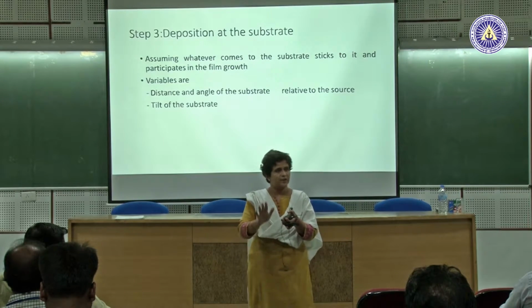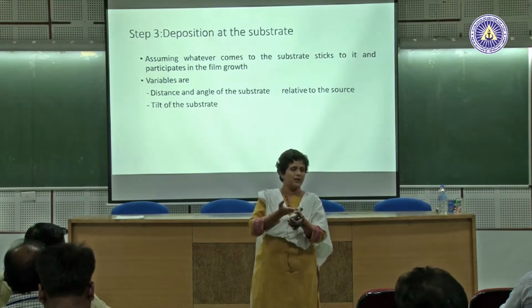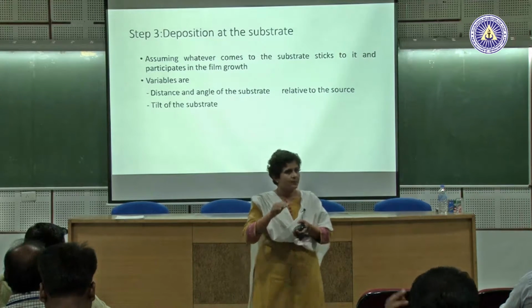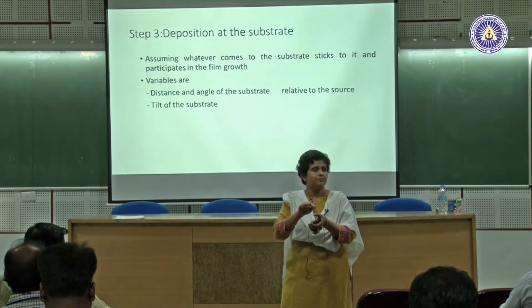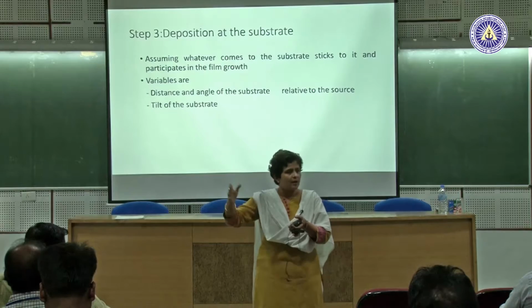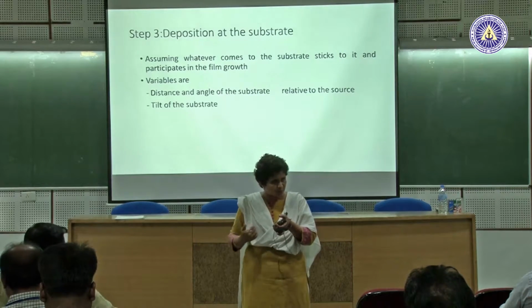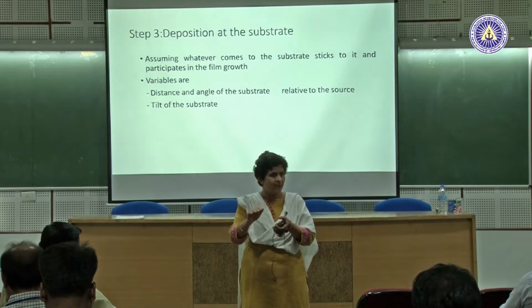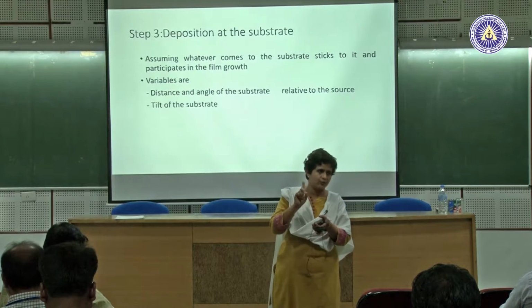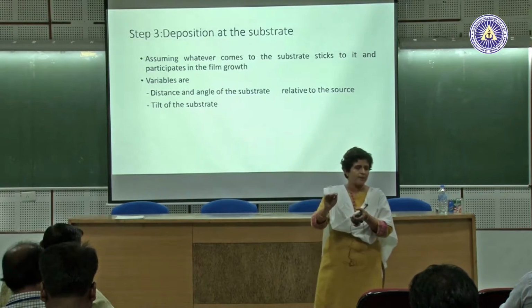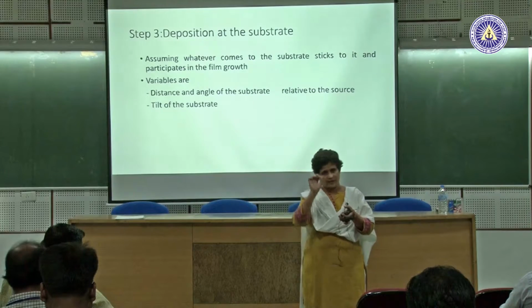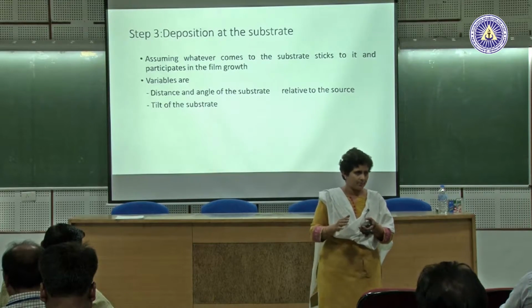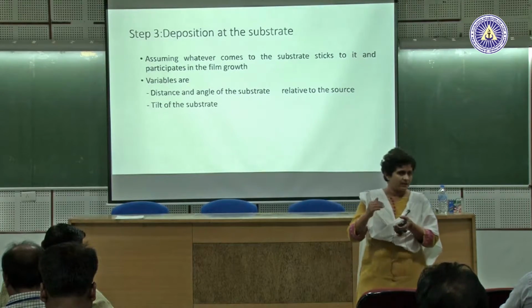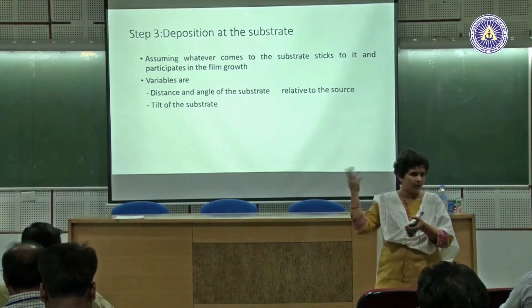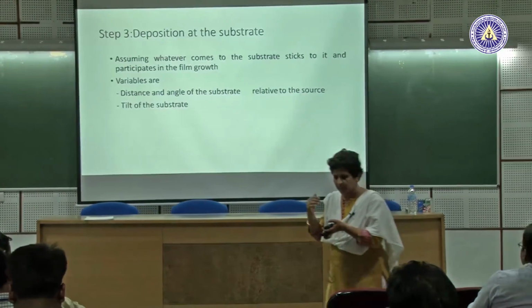If you have a clean surface and you have maintained it, and that is why as soon as you clean it, you put it under the vacuum, because under the vacuum, to grow the same oxide on the surface, it would take maybe a day or so. So, you have enough time to bring in your material and deposit a film. Okay. So, that is the first point, your surface should be cleaned for a good bonding. Now, if I have maintained that as soon as I clean the surface, I have put it in vacuum and I have started my pump, and the surface remains clean for a few hours or something, and one can do the calculation using gas kinetics theories on that.